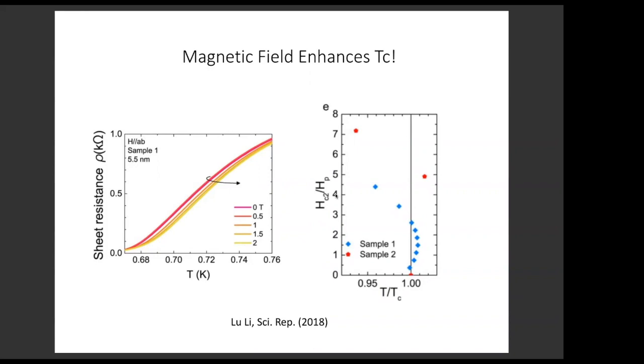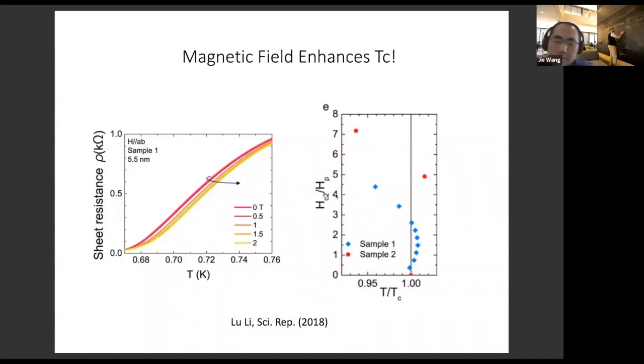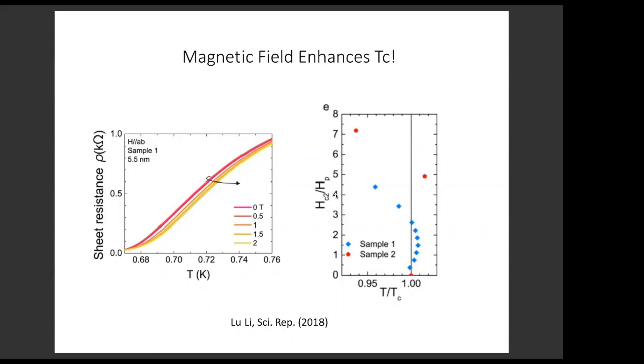For example, if you look at resistance as a function of in-plane magnetic field, you see that the superconducting transition occurs at higher temperature under in-plane magnetic field. So the right panel is a plot of the TC dependence on magnetic field, and you see clearly, with now many, many more data points, that TC actually increases first when you apply a small in-plane magnetic field. Next slide.